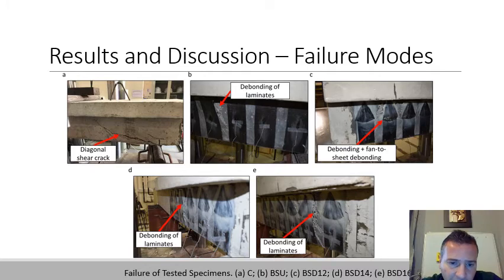And for the ones with the other diameters of dowels, you can have debonding of laminates locally between the top and the bottom, but it happens at a later stage in loading. And this one again shows debonding of laminates, but at a higher level of loading. Now what I want to say is that we did not apply load, we applied displacement control. The beams were tested under displacement control at 1 millimeter per minute, I think.